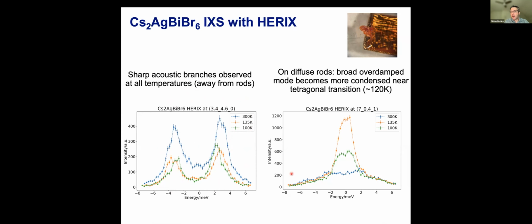But if we look on the rods, so if we pick reciprocal lattice vectors where the rods are intense, we find that at high temperature, there's indeed this very broad signal. It's wider than the energy resolution of HERIX. You can see that it extends over several milli-electron volts here. It's got this almost plateau-like shape that extends about 2 to 3 milli-electron volts. And when you cool down towards the tetragonal transition, this picks up intensity and somewhat condenses. But the weird thing again is that it doesn't condense at a single wave vector, but rather at all wave vectors along the rods. And then when you cool down across the phase transition, this gets a little bit weaker, but persists for some range of temperature.